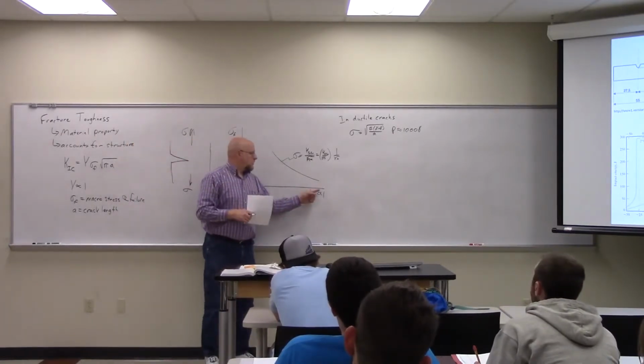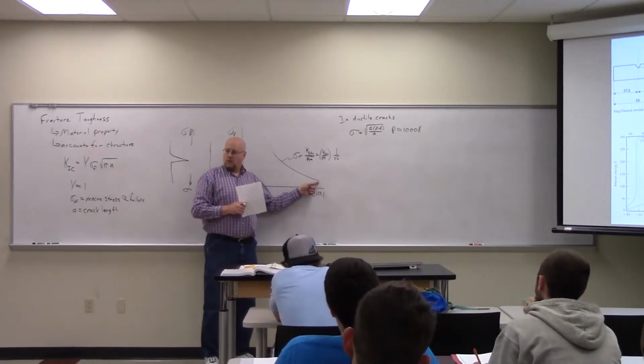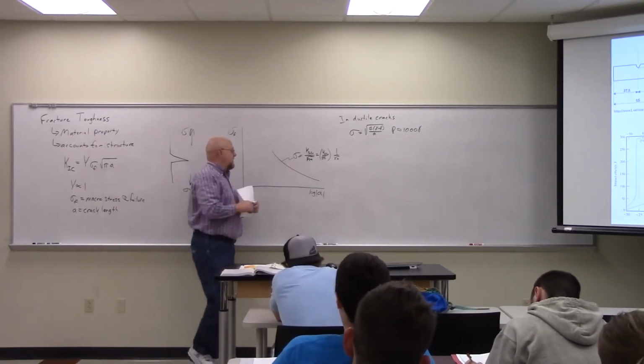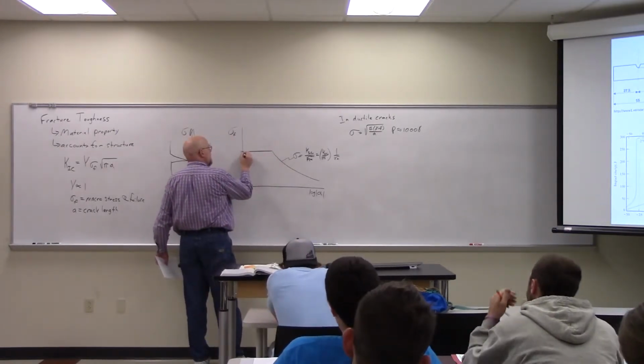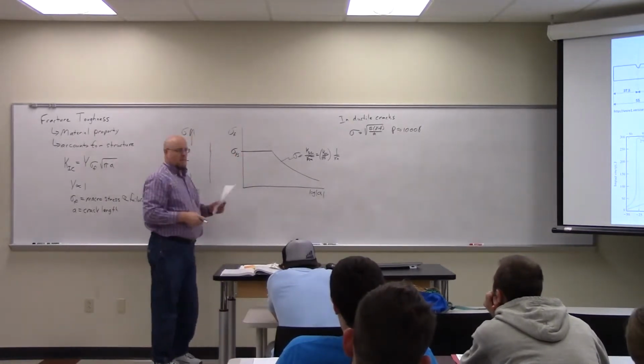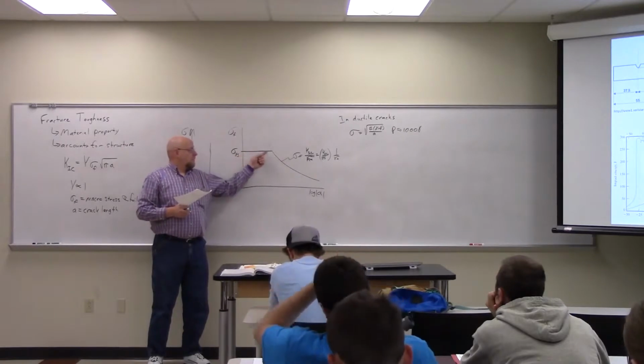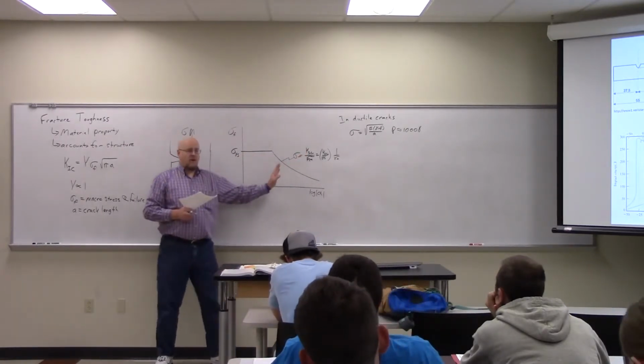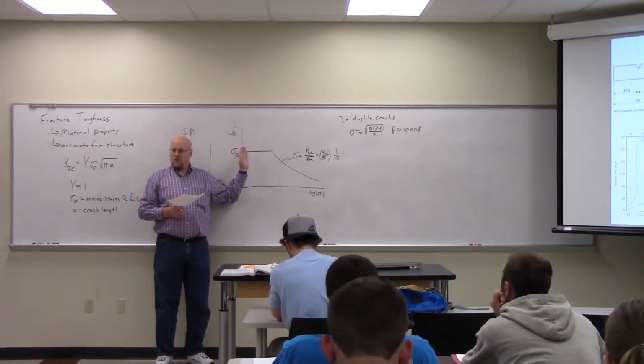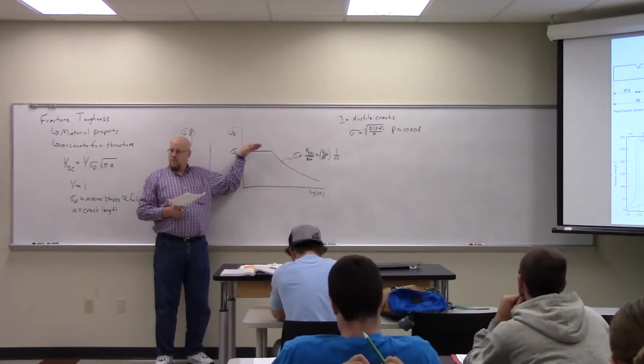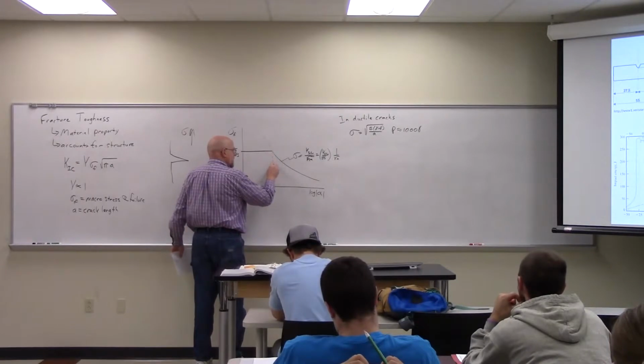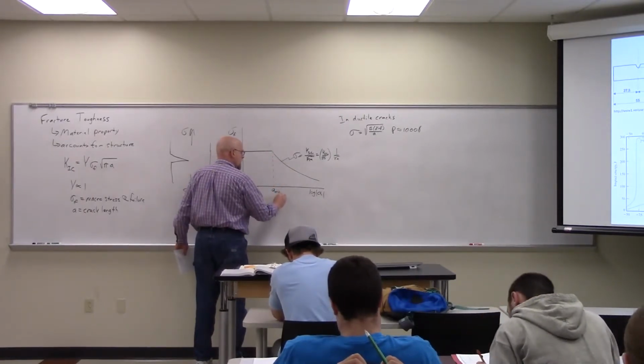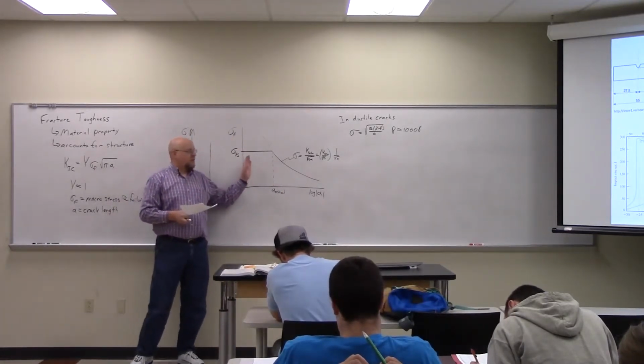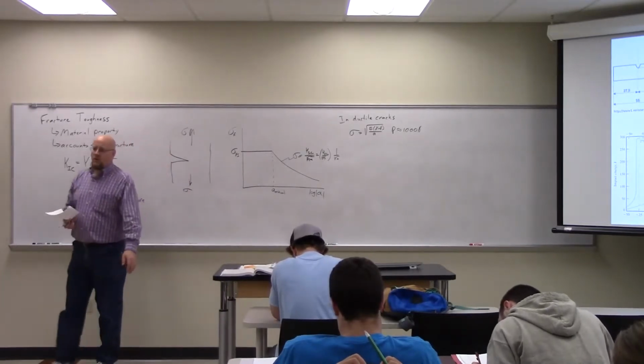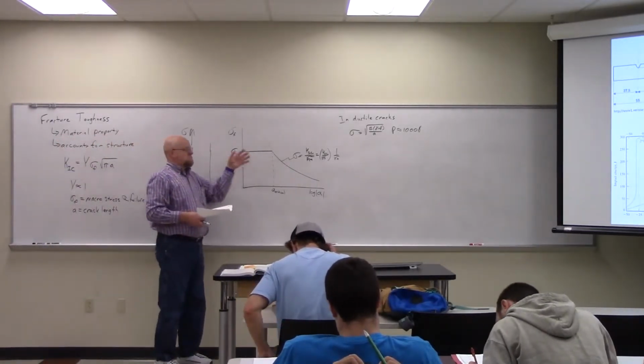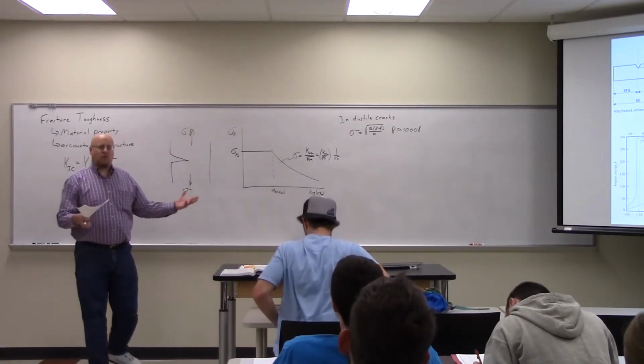So if I have very large cracks, the stress at which it fails is going to be small. If I have smaller cracks, it's going to be larger. And eventually, this curve comes across at the yield point. At some point, the cracks are small enough and the fracture toughness large enough that those small cracks aren't enough to cause enough stress concentration, and I just get general yield out of the material. So only when the cracks are bigger than this critical size will the crack length actually have an impact on the strength of the material. Anything smaller than that, it doesn't matter that the cracks are there, because they don't concentrate the stress well.